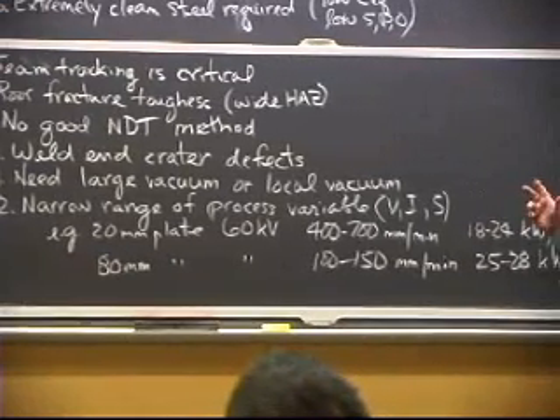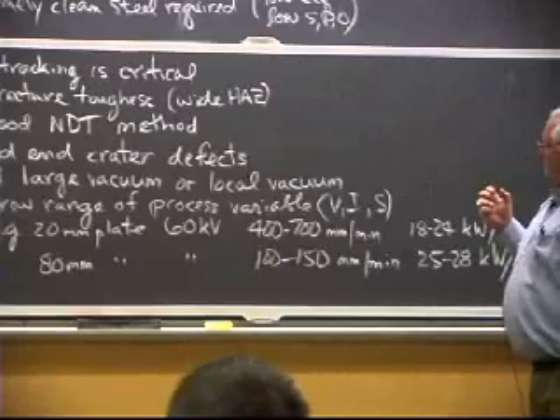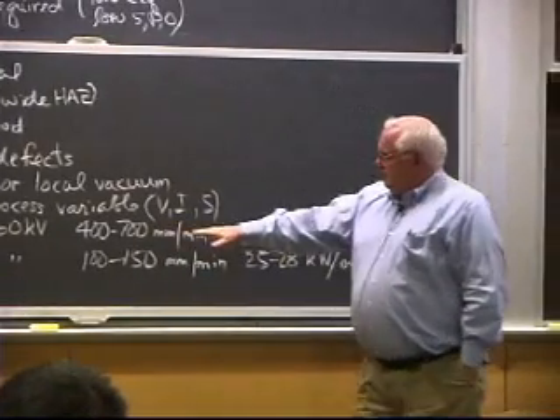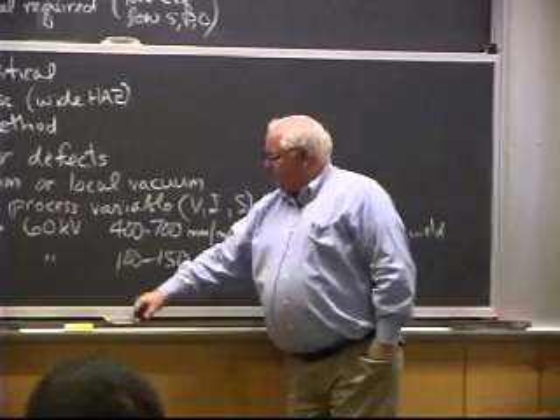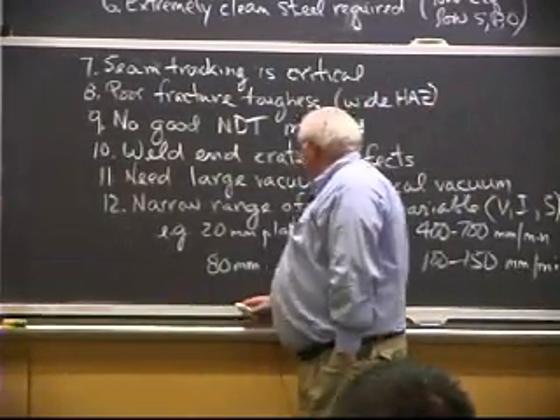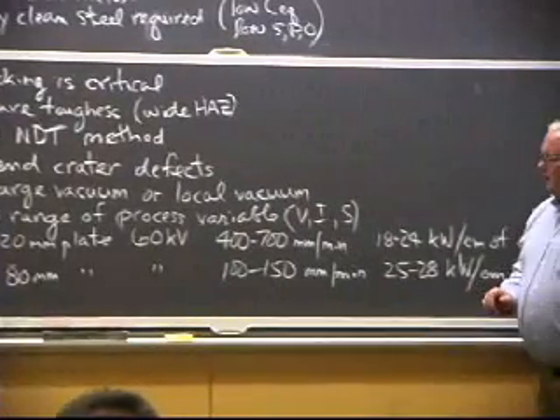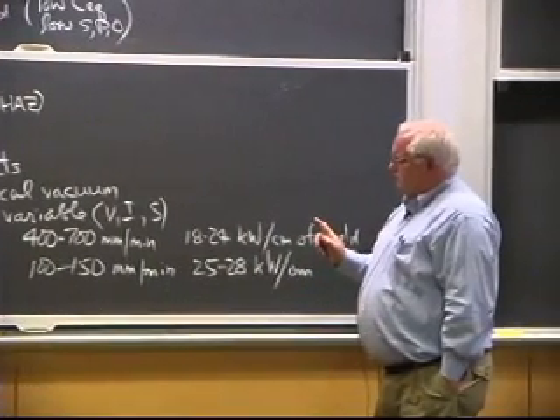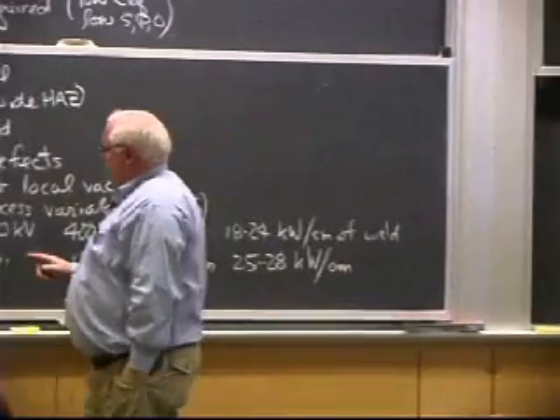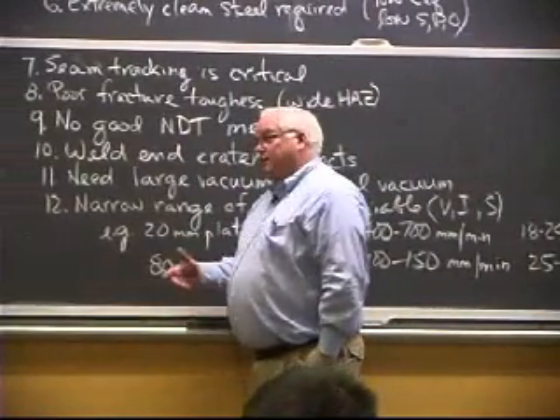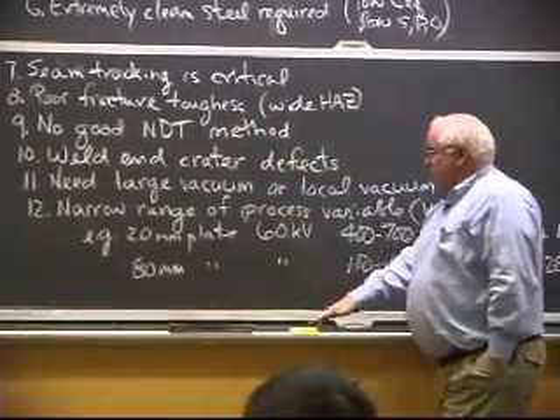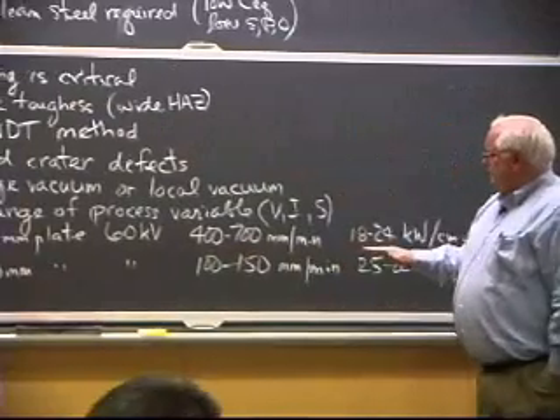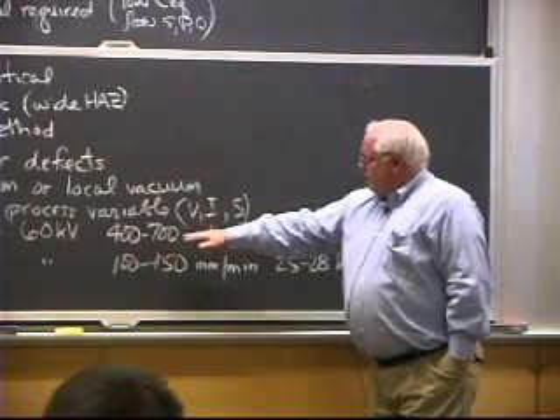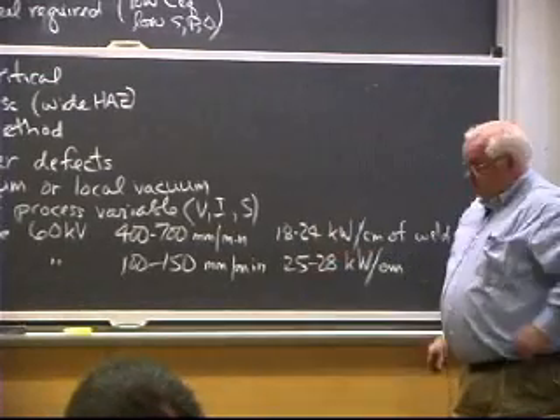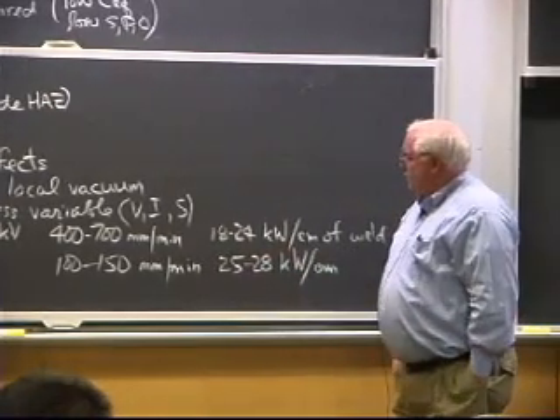And it turns out they found that as they went to thicker and thicker plate, the processing parameters that you could use narrowed in terms of voltage, current, travel speed, and whatnot. On a 2 centimeter plate or an 8 centimeter plate, so 8 centimeters is like 4-inch plate, this is relatively thin, only 3 or 4-inch plate. Anyway, you could have almost a factor of 2 in travel speed and a 1/3 variation in your power per centimeter of weld, and still get a good weld.